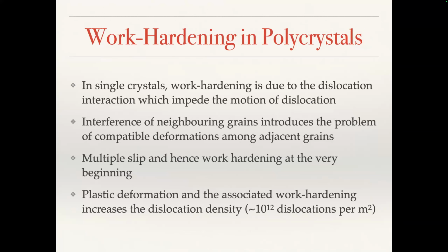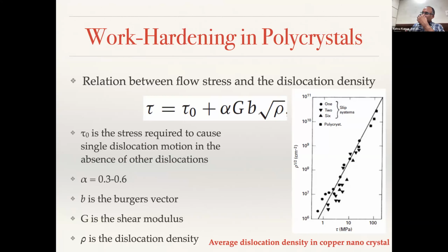Yes. Sir, one question. We are saying that in solid solution strengthening, yield strength is increasing because of the impurity adding. In that case, like we have seen before, we are reducing the grain size. No, grain size reduction is independent of solid solution strengthening. In grain size reduction, you can have a single material. It need not have another material. Even if it is pure copper, because you have more grains, the dislocations come and interact with the grain boundary.